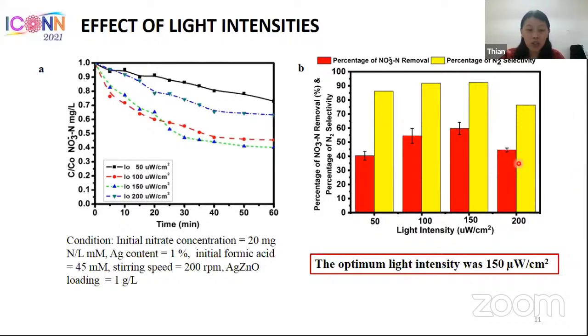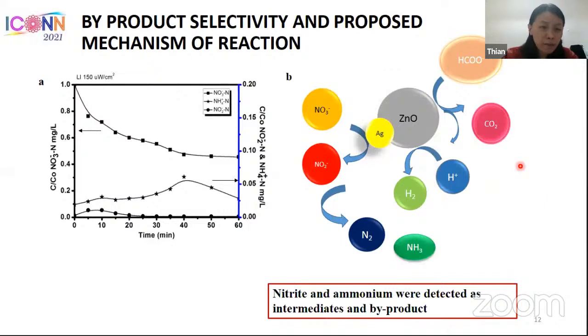recombination. So here, this is a representative graph of the time-dependent nitrate photoreduction, and the byproducts and the intermediates which it forms. As we can see, as nitrate is being reduced, the bottom line is nitrite. NO2 is being formed in the beginning of the reaction, but slowly after that it faded. At the same time, ammonium is slowly accumulating towards the later stage of our experiment. So hence we propose this is what is happening.